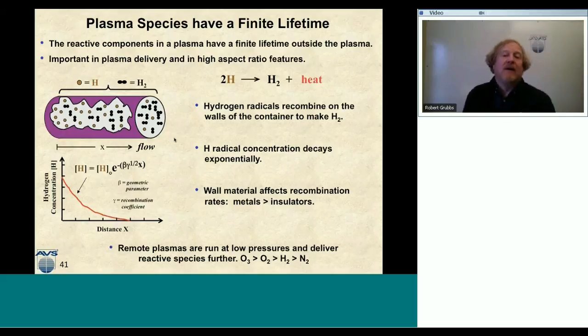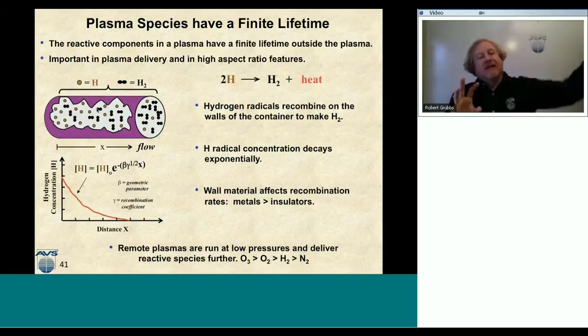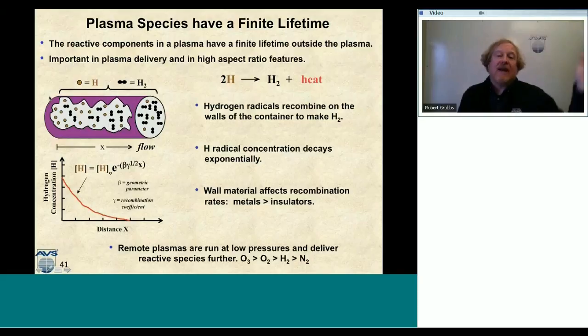Hydrogen is my one example here: hydrogen radicals, or atomic hydrogen, will recombine on the walls of a container to make H2. So I have a surface, I come in with hydrogen radicals, and hydrogen radicals will just decorate and coat the surface. And when another hydrogen radical comes down and hits the surface, it will react with that hydrogen on the surface and then desorb and form H2. So if you're using hydrogen radicals, they can recombine on the walls of your surface or the walls of your trench, and that decay is exponential as you go down a trench or down the walls of a reactor. And the rate at which that recombination takes place is usually much faster on metals than insulators, and that's also why you typically run remote plasmas at lower pressures.